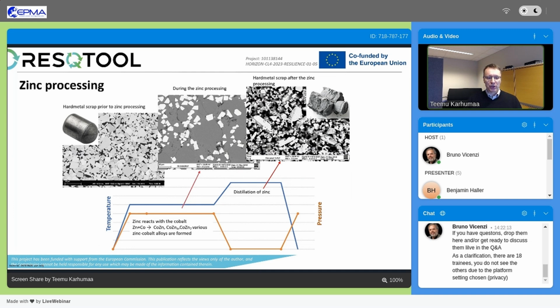The temperature curve and pressure curve could be something like this. We increase the temperature under nitrogen atmosphere, let the zinc react with the cobalt binder. Then we increase the temperature, decrease the pressure, so that the zinc starts to boil and evaporate, and then it's recovered and condensed in the second batch, so that we lose as little zinc as possible.